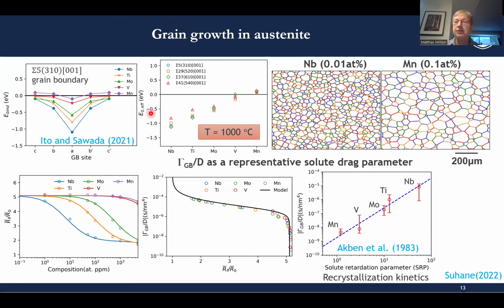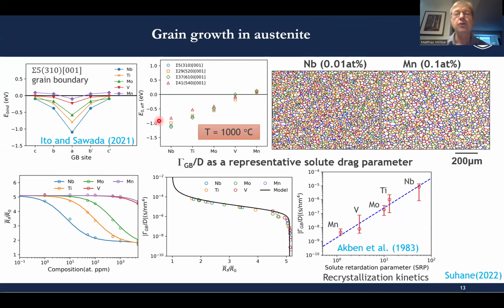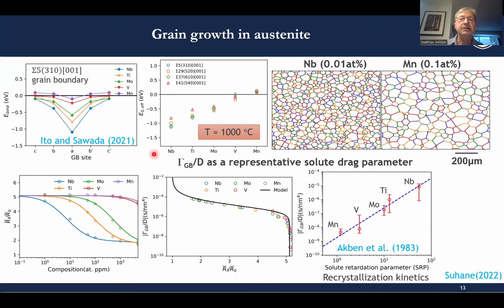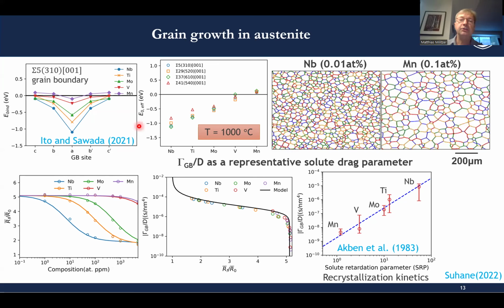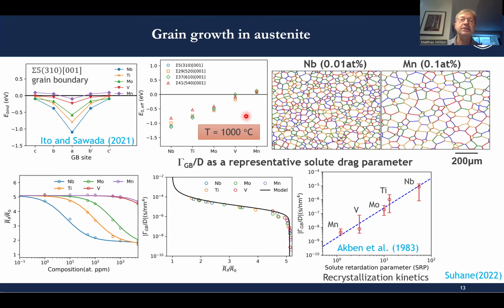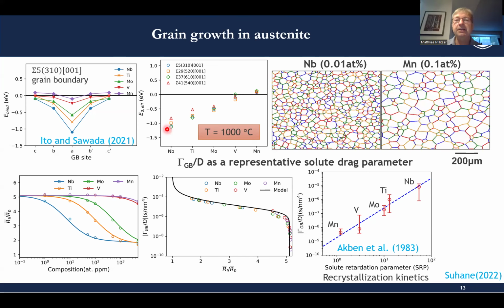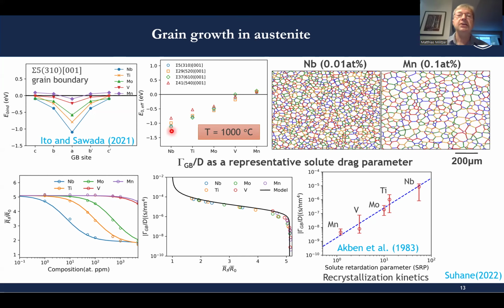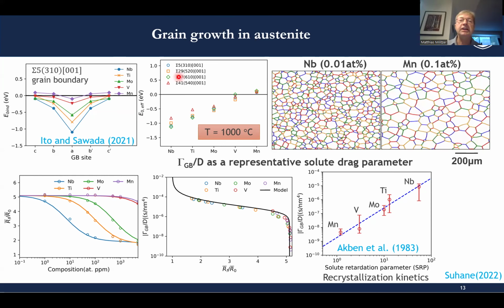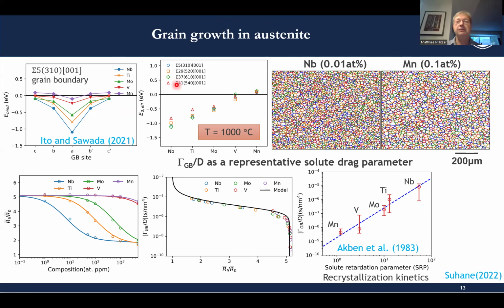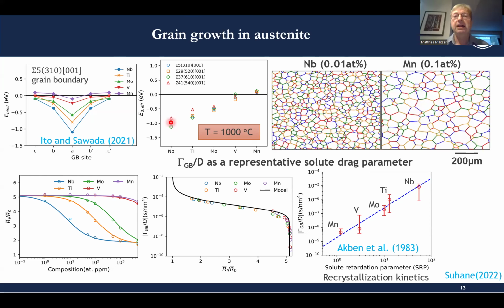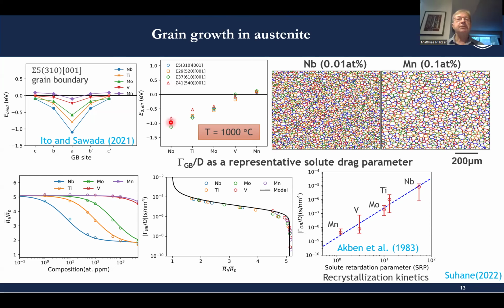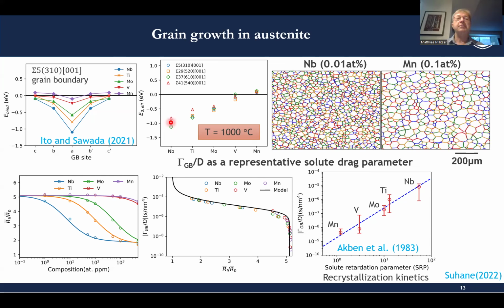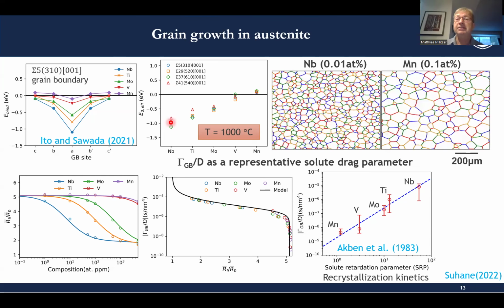And then we use this concept that I just illustrated for gold to calculate the effective value of this binding energy in Cahn's solute drag model here at 1,000 degrees. We see the trends that we see for sigma 5 boundaries are replicated in terms of the alloying elements. For different sigma boundaries, there's a little bit of variability when we have different sigma boundaries for a given alloying element. But for trend predictions, basically, even the sigma 5 grain boundary is representative.